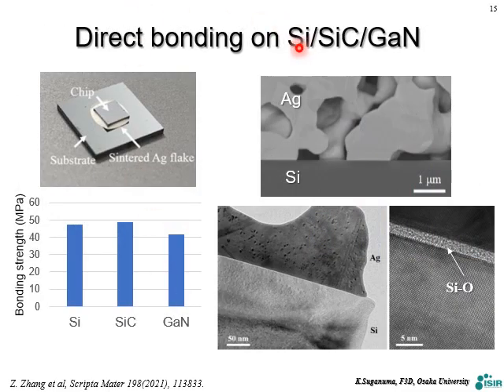And for other materials, we have tested many materials, silicon carbide, gallium nitride, like this. And silicon has very high strength. Silicon carbide, again, is very high. And for gallium nitride, we don't need any metallization when using silver. So this is the interface. Of course, there is no reaction, no intermetallic compounds between the two materials.